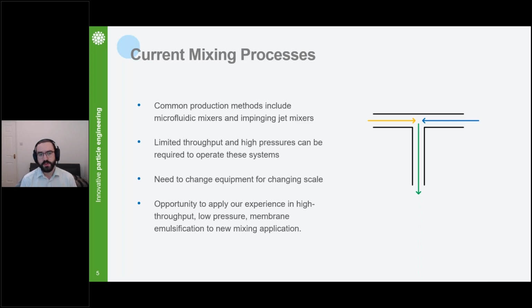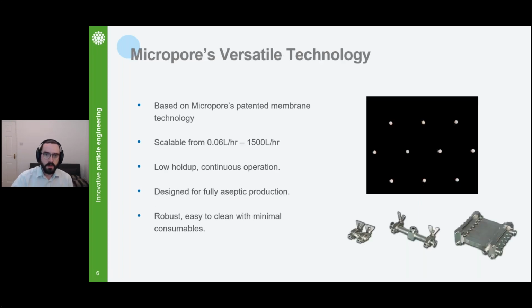So we saw this as an opportunity to apply our experience with membrane emulsification, essentially forming droplets and emulsions, to apply that membrane technology to forming these lipid nanoparticles. So what we've developed is a platform that's based on Micropore's patented membrane technology. We've developed this using our stainless steel membranes that you can see on the right-hand side of the screen there. These essentially are stainless steel tubes that we have very precisely formed pores in, controlling the size and the distribution of those pores to a very high degree, as you can see from that micrograph.